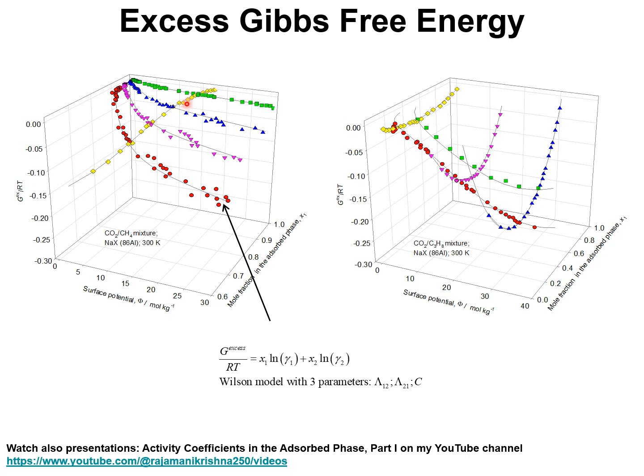The yellow diamonds are CBMC simulations for a set of conditions in which the bulk fluid phase is held constant at a fugacity of 1 megapascal, and the composition in the bulk gas phase mixture is varied for CO2 from 0.05 to 0.95.